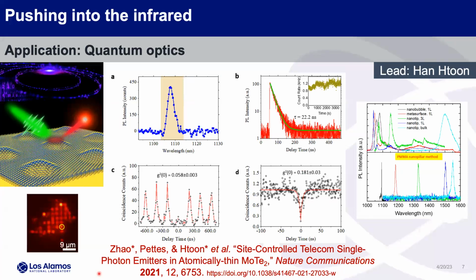in an array on the substrate. And then when we look at the InGaAs CCD, we put some filters on it and then just image the whole thing and see where wavelengths beyond, I think this was wavelengths beyond 1300 nanometers, where those spatially line up. They match up pretty well with where these nanopillars were put on. So we were pretty happy about this as a proof of concept that you can do this same kind of work in the infrared that's relevant to industry.